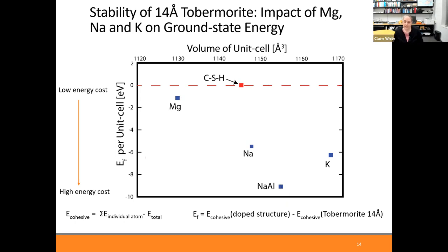The other thing that we did here is we calculated the cohesive energy for all of the different structures we had. And then we looked at differences in the cohesive energies between different structures to get a sense of the impact of that substitution on the stability of the material, the phase. And specifically, if you do the substitution, do you have a decrease in this formation energy? If so, that means that there's an energy penalty to having that different atom in your structure. And overall, that means that your structure is less stable. It could be more prone to change over time.